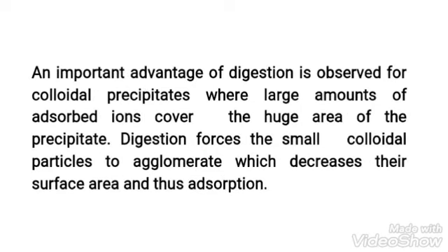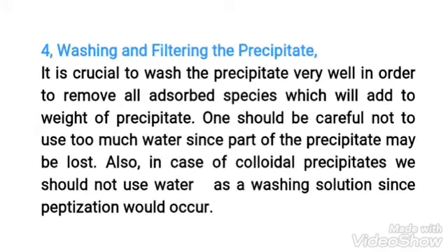An important advantage of digestion is observed for colloidal precipitates where large amounts of adsorbed ions cover the huge area of the precipitate. Digestion forces the small colloidal particles to agglomerate, which decreases their surface area and thus adsorption.